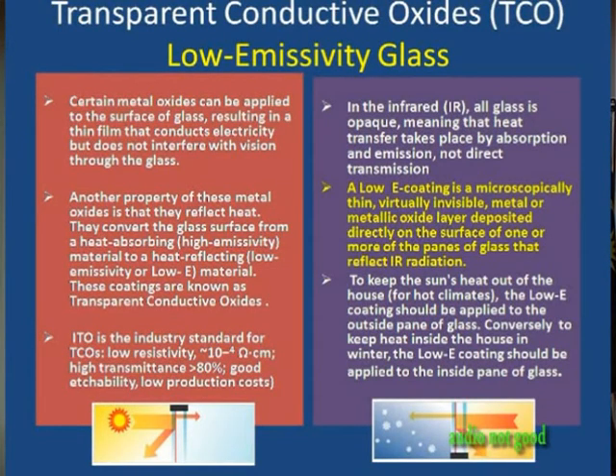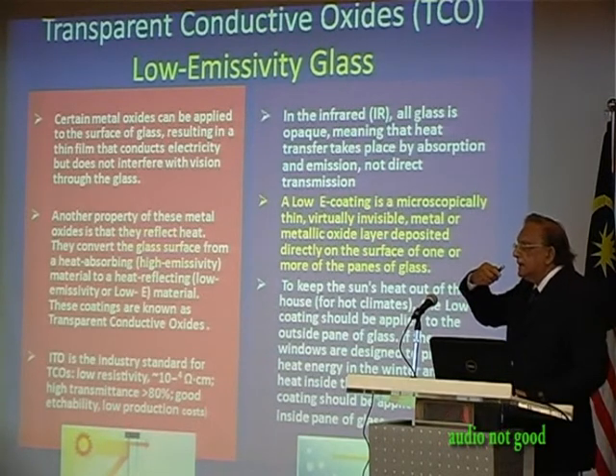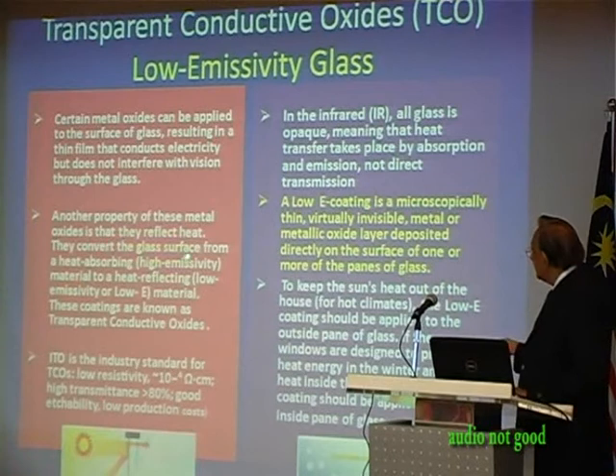I was talking about low emissivity glass. Basically, you are applying the tin oxide as a very thin coating on the glass. This is IR reflecting. It reflects heat rays. What does that mean? That means converting the glass surface from a heat absorbing, high emissivity material to a heat reflecting, low emissivity material. And if you have this, you can keep the sun out during summer, and you can keep the heat in during winter.